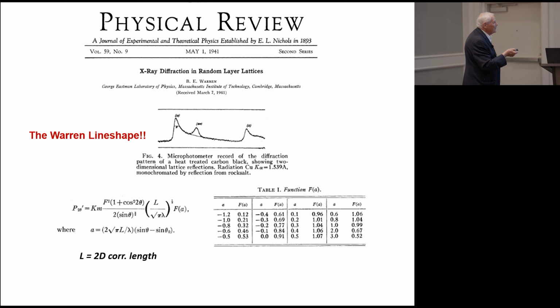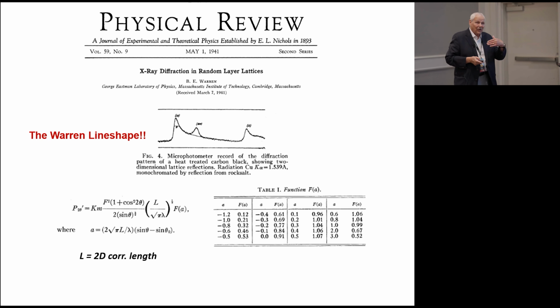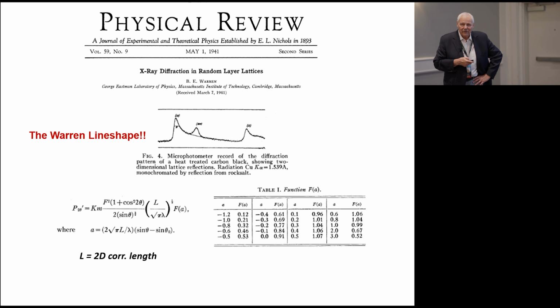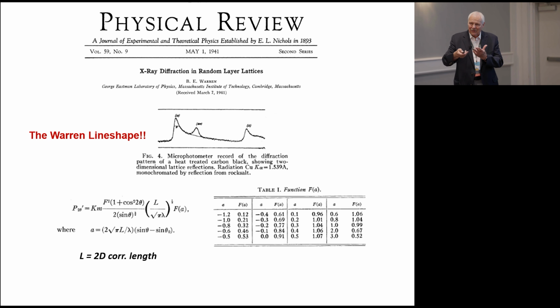for this funny material. This is actually a diffraction pattern of carbon black, which is a material which has graphite-type layers which are randomly stacked in 3 dimensions, so they're actually strictly 2-dimensional material. And so Professor Warren was able to show that this weird sawtooth line shape is derived from this type of stacking sequence where you have really just scattering from a two-dimensional system. He was studying carbon black, and I guess we can forgive him for not having discovered buckyballs, right? Because there's a teeny tiny fraction of buckyballs hanging out in carbon black.